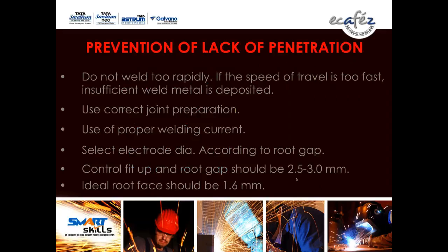Prevention of lack of penetration. Do not weld too rapidly. If the speed of travel is too fast, insufficient weld metal is deposited. Use correct joint preparation. Use proper welding current. Select the electrode diameter according to the root gap. Like if your root gap is 2.5, then you should use a 2.5 diameter electrode. If your root gap in the butt joint is 3 mm, you should go for the 3.15 mm diameter electrode.